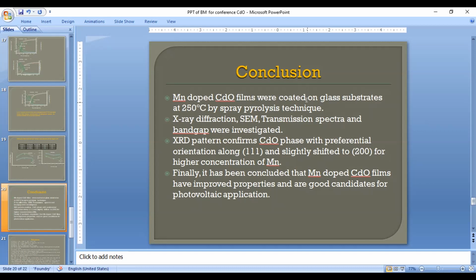If we increase the concentration level to 0.03, the transmission also reduces, because I already informed that the transmission is good enough only for 550 nanometer to 900 nanometer. Finally, it has been concluded that the Mn-doped CdO films have improved properties and are good candidates for photovoltaic applications. So in future, it will be available for CZTS, CIGS. Some research is going on for CTS and CZTS also. That's why this is my area.